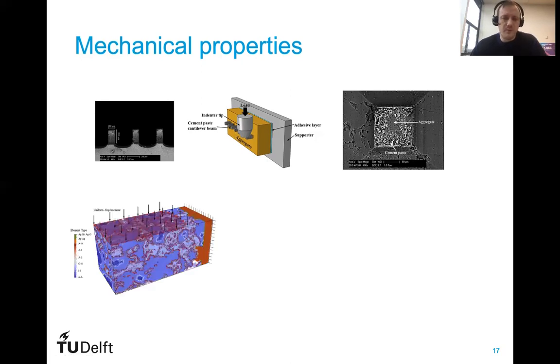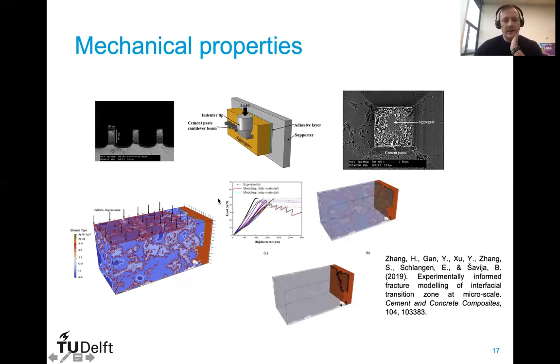onto the aggregate particle. We could then use our lattice model to simulate the same process, and from that, calculate back the properties of these contact elements between our lattice mesh of the paste and our aggregates. And this gives us all the properties needed to simulate mortar on the following scale. So we calculated properties of hydrated cement phases, and from that we can estimate the properties of the cement paste.